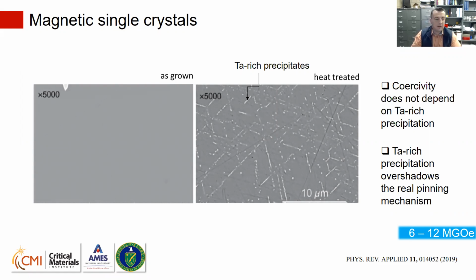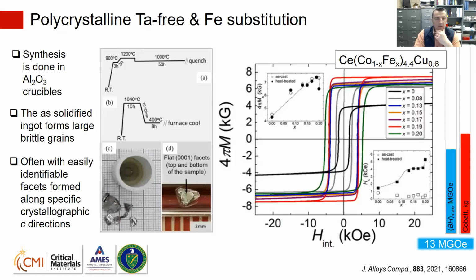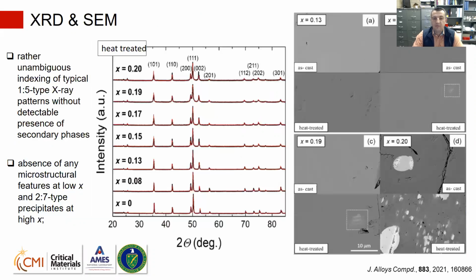They are degrading, or they are developing their subgranular microstructure, but in fact it's not tantalum. So we decided, no, that's not a good result. We have to avoid tantalum, and we have to do something differently, so that we can see the reason for the extrinsic properties itself. And we decided to do alumina crucible synthesis, and to test how much iron we can substitute into those 1,5 type systems. As you see, the indicator is showing that we reached 13 megagauss oersted, and we were able to reduce cobalt even further. Definitely we avoided tantalum, but results were very confusing again.